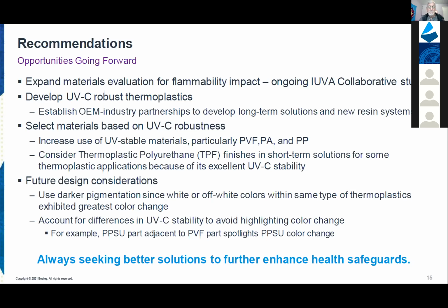if you can design parts using the PVF, the polyamide, the nylon, or the polypropylene, if there's not an issue with flammability, and there can be, but on some applications, you only need to meet vertical Bunsen burner, and so that's good. PVF is never an issue, but let's use those if we possibly do that. Finally, our thermoplastic polyurethane finish is a good short-term solution. It does have good flammability properties, and it was just solid as a rock under UV exposure.